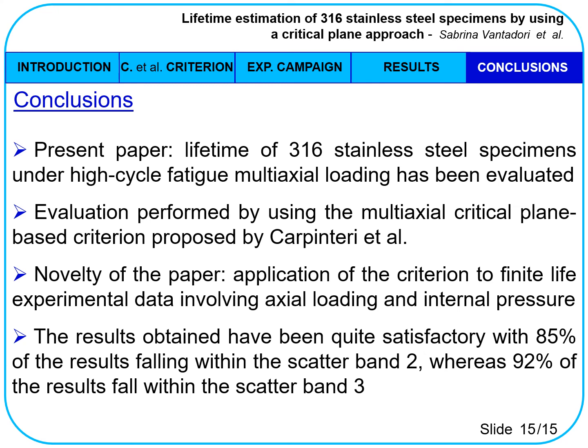The results obtained have been quite satisfactory, with 85% of the results falling within the scatter band 2, whereas 92% of the results fall within the scatter band 3. Although further verification is needed for different materials.